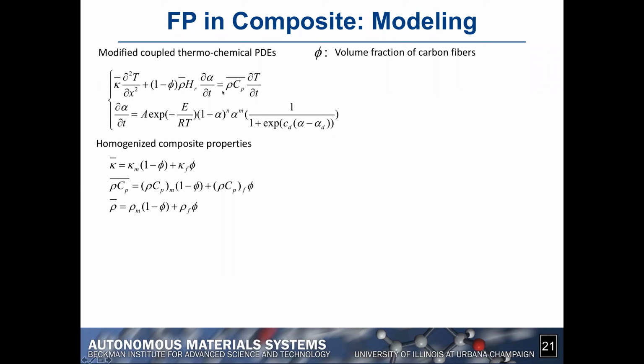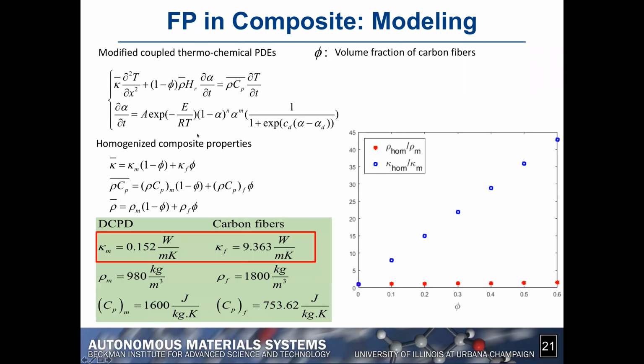Obviously, the more fibers we have, the less matrix we're going to have. And therefore, we have a term 1 minus phi that will scale the heat generation associated with the exothermic reaction of the matrix. The second equation is absolutely identical to what we had before. Now, there's a major difference between the thermal properties of the matrix and the thermal properties of the carbon fibers.